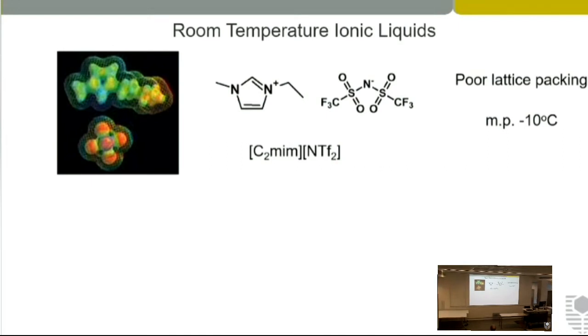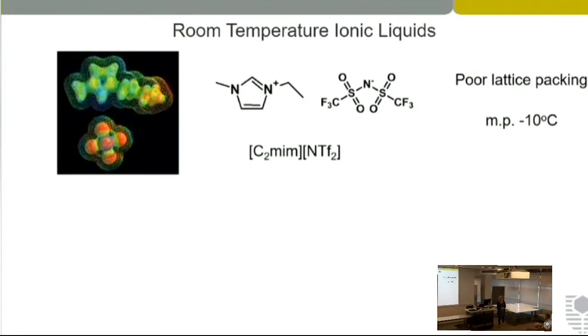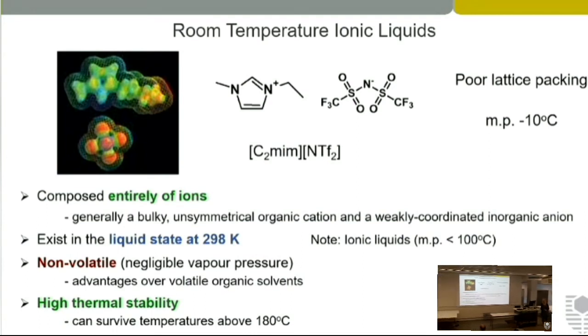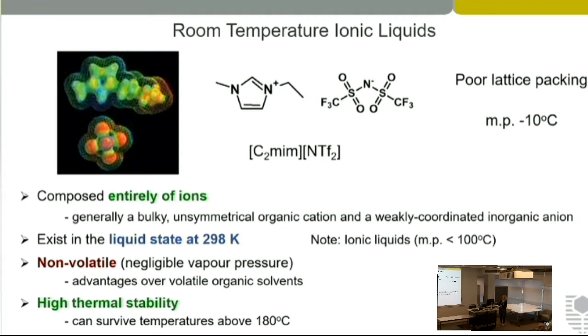Ionic liquids are similar to salts in that they're made up entirely of cations and anions, but as you can see, the chemical structures of these ions are very different to sodium chloride, much larger molecules. Because of this, they have very poor lattice packing. This particular example, an ethyl imidazolium with an NTF2 anion, has a melting point of minus 10 degrees Celsius, so at room temperature it's very clearly a liquid instead of a solid. We can think of them as solvents rather than just electrolytes that you dissolve into a solvent. They're composed entirely of ions, normally a bulky asymmetric organic cation and a weakly coordinated inorganic anion.